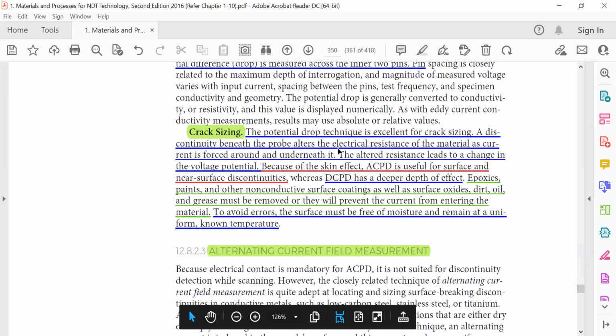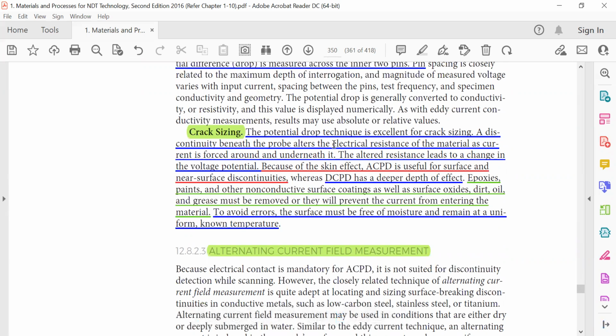Crack sizing. The potential drop technique is excellent for crack sizing. A distinct discontinuity beneath the probe alters the electrical resistance of the material. As current is forced around and underneath it, the altered resistance leads to a change of voltage potential because of the skin effect. ACPD is useful for surface and near surface discontinuities, whereas DCPD has a deeper depth of effect.